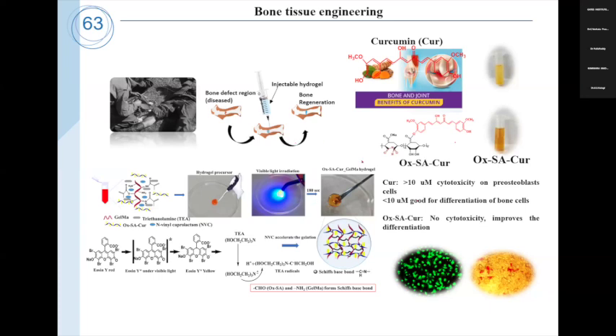From this study, we observed that free curcumin at greater than 10 micromolar shows cytotoxicity in pre-osteoblast cells. In our study, the conjugates at less than 10 micromolar show no cytotoxicity, improve osteoblast differentiation, and form bone-like nodules.